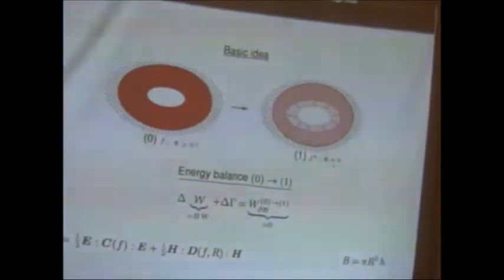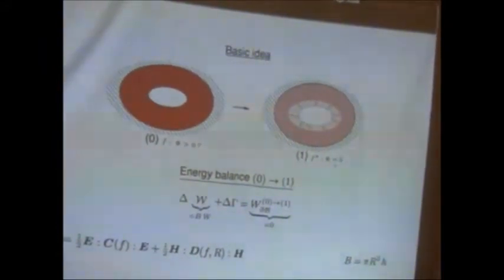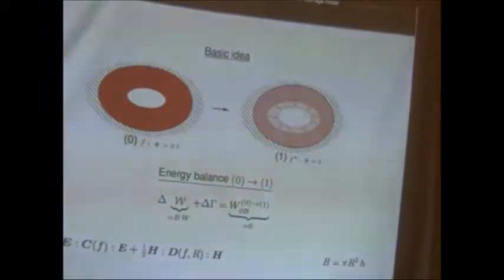There are other possibilities, but having this, the question now is how can we develop a damage model based on this? And here we borrowed an idea which is very common in linear fracture mechanics. It goes as follows. Assume we have such a volume element with a prescribed displacement field, and this volume element is under a lot of stress and starts claiming that it doesn't take it anymore, and we say, okay, you can relax, but the only option you have for relaxing is that the void has to grow.